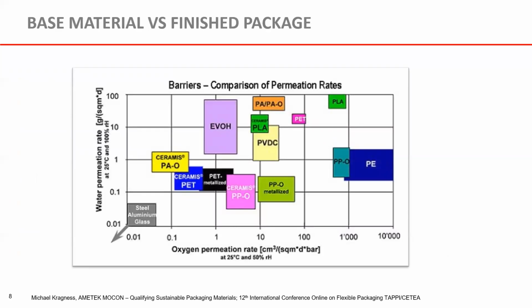So now, what's the process if we want to design something? As you see in this graph here, there's a bunch of very well-known commodity packaging materials, the water vapor transmission rate versus the transmission rate of oxygen. Polyethylene is a very high transmitter for oxygen, and it's an okay moisture barrier. And then you have steel or aluminum or glass, which is basically very low or essentially zero for moisture and oxygen.